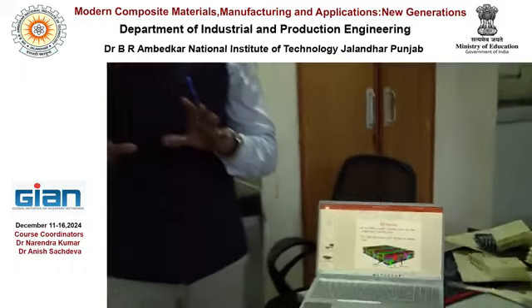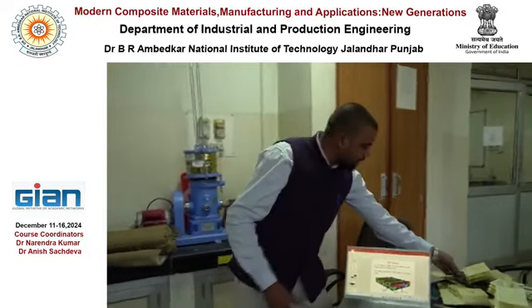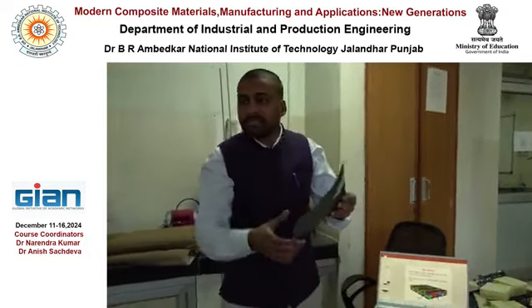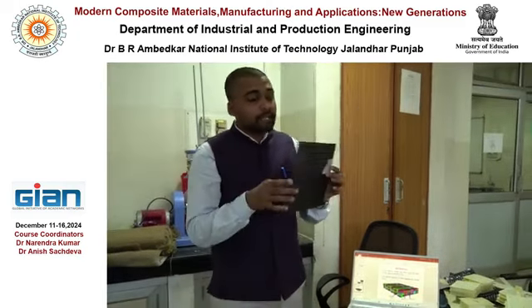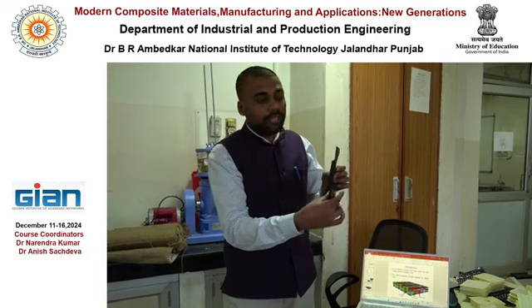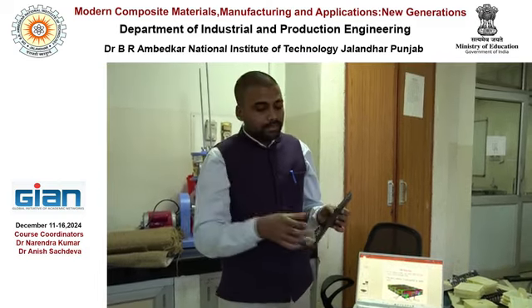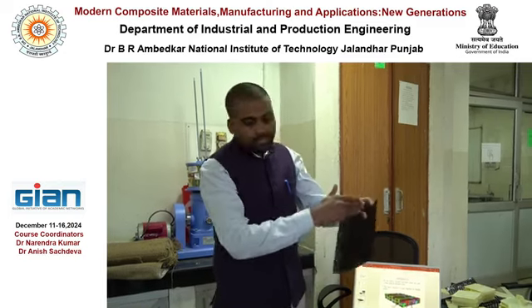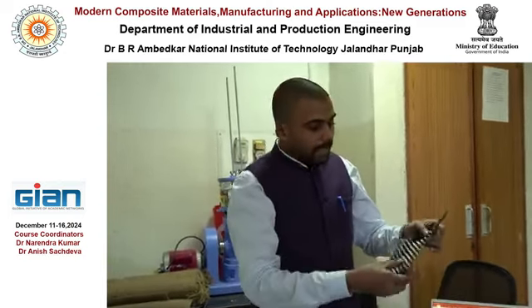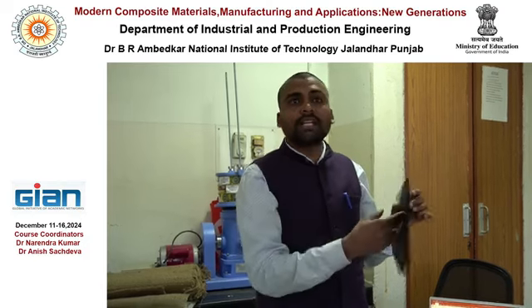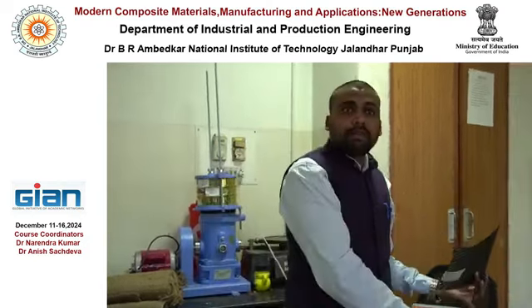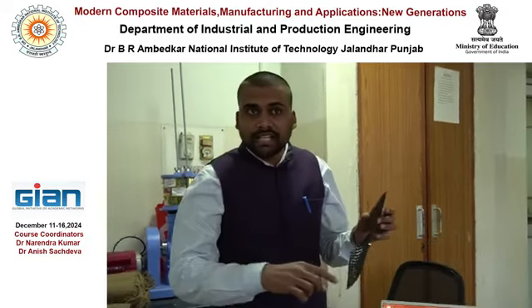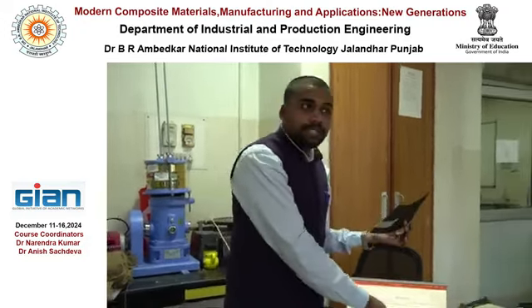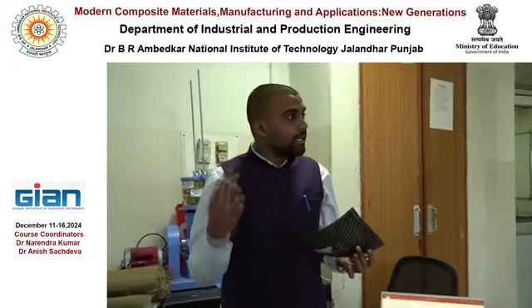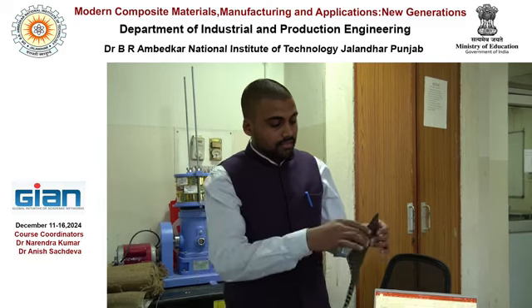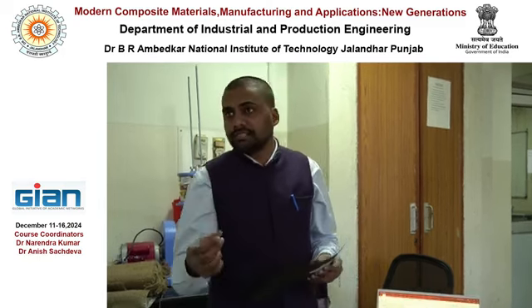3D fabrics are fabrics having, a normal fabric has length and width. It also has thickness, right? But the thickness of a normal 2D fabric is a maximum of 2 times the yarn thickness, because you have yarn in the X direction and Y direction. But why do we call this particular fabric 3D? Because it has a length dimension, a width dimension, as well as a thickness dimension, and the thickness dimension is multiple times your yarn thickness.